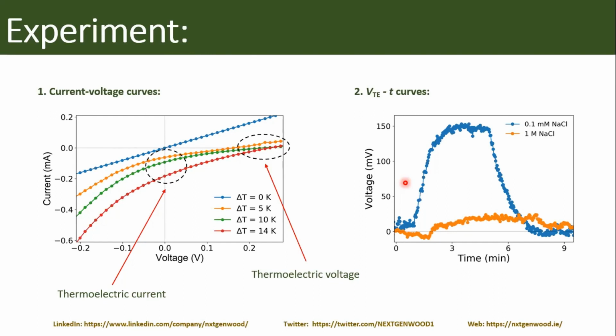Yes, totally support this concept. And just like I mentioned to you before, the current showing on these IV curves is time dependent. This was made using an electrochemical potentiostat, where you can control the scan rate. And if you start changing it, you see that the current is changing. That's why we switched to using the open circuit voltage as a function of time, because it gives more reliable data. The current is always there because the circuit is closed, but it's very difficult to measure it and convert it to something similar to what we use for batteries, for example. It's not that well defined. Okay, I agree with you.